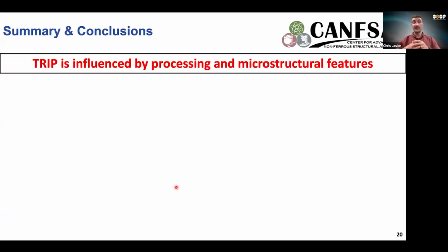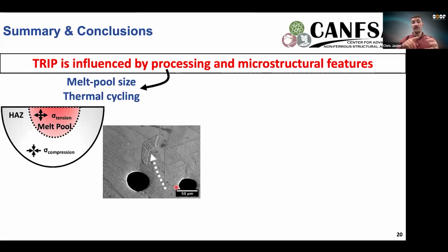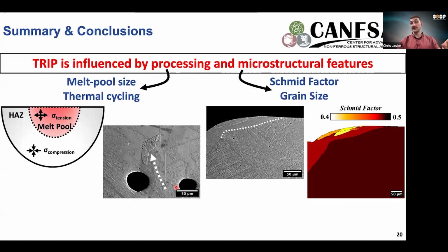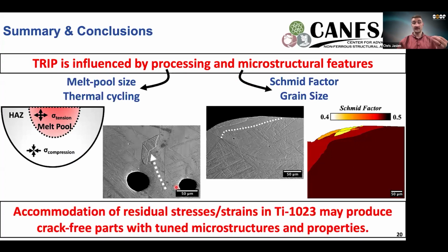So in summary, we've seen that this TRIP mechanism is influenced by both processing, whether that be the size of the melt pool as well as the thermal cycling, as well as microstructural features such as the Schmid factor or grain size that I previously talked about. So based on this work, we've identified that the accommodation of these strains and stresses in this material may produce crack-free parts with tuned microstructures and properties that we haven't seen in any materials before.